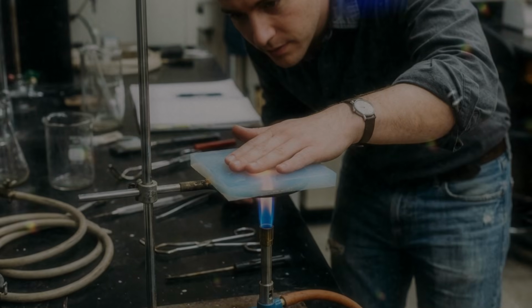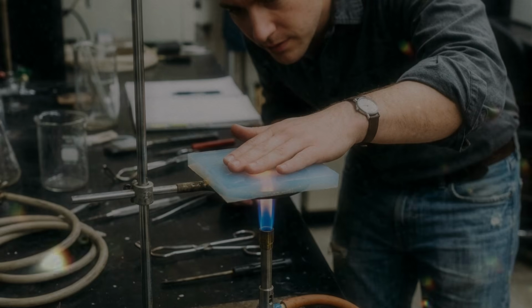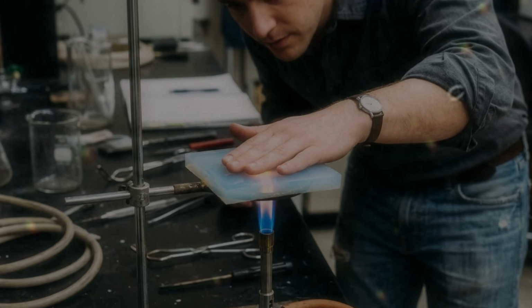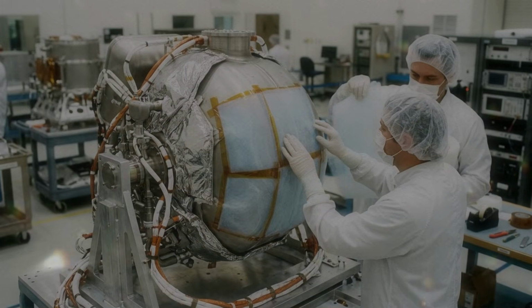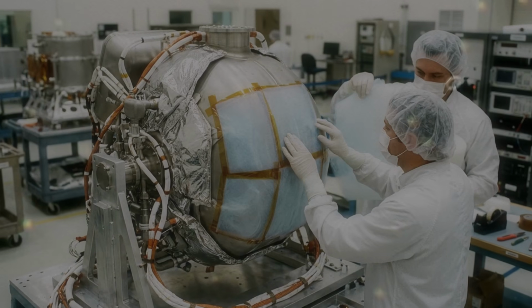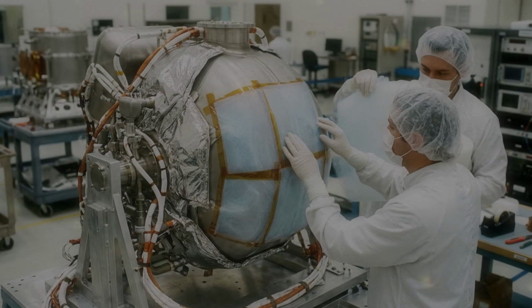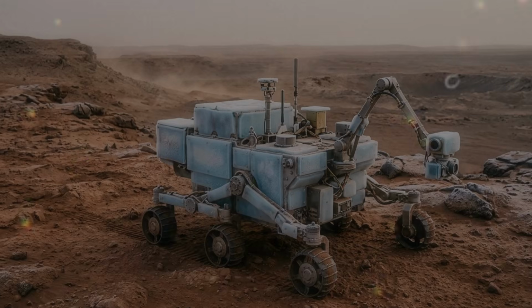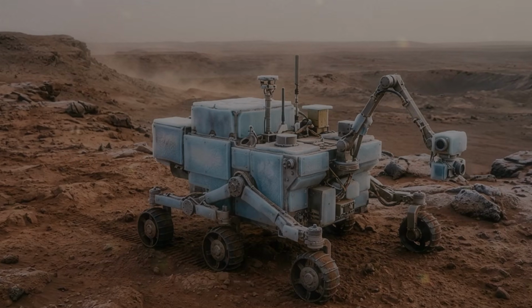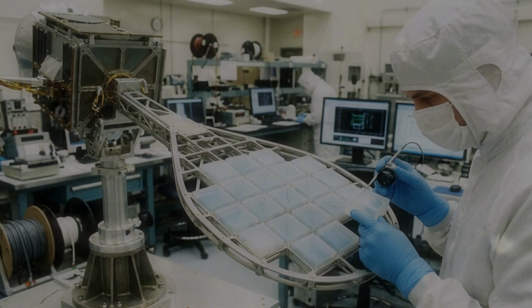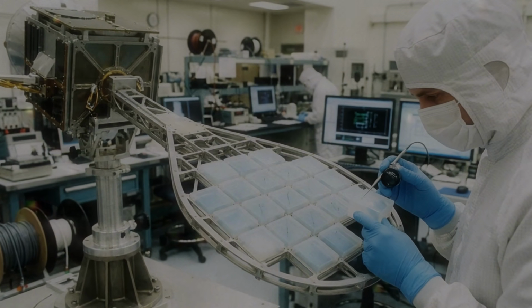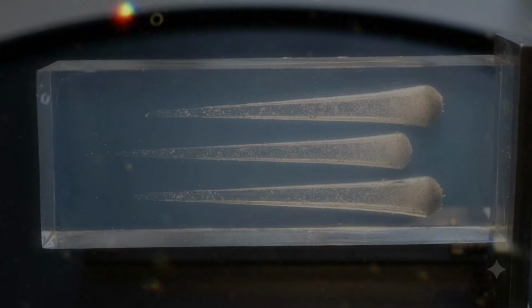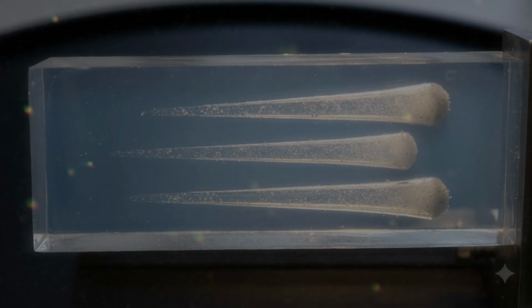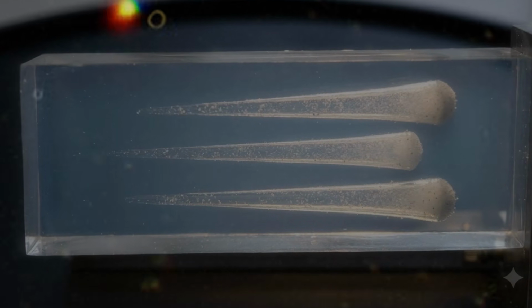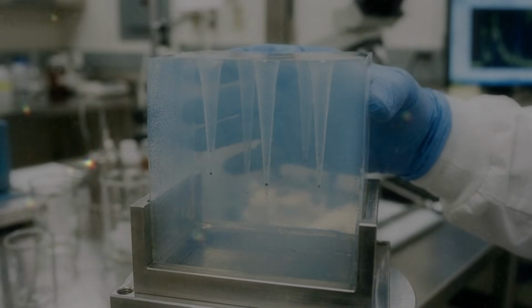The silica building blocks react with water and then begin joining to one another. At first they form tiny clusters. Those clusters grow, branch, and meet other clusters. Given the right conditions, the connections eventually spread across the entire container. The liquid is no longer simply a liquid with particles floating inside it. A continuous solid network now reaches from one side to the other. This transformation is called gelation. Before gelation, the mixture can flow. After gelation, it holds its shape even though most of it is still liquid.